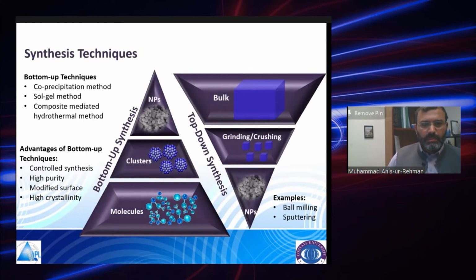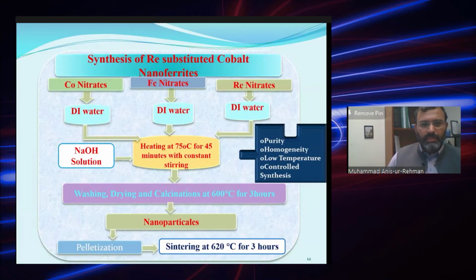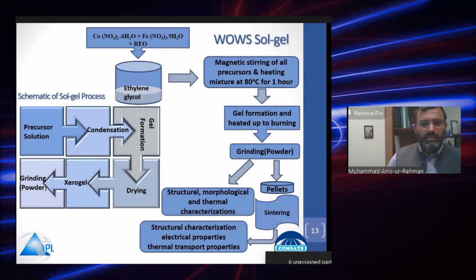Synthesis techniques are bottom up and top down. Bottom up methods are usually economic and can be easily handled. The materials we have prepared were made by two wet chemical methods. The first one is the co-precipitation method. The nitrates of the respective elements were dissolved in deionized water with a molarity of 0.4, and then heated at 75 degrees. After getting the precipitates, these are calcined and pellets are made for further characterization. The beauty of co-precipitation is that we can get purity and homogeneity, and it is a low temperature method. The other method we have utilized is the WOWS sol gel. It is a simplified form of the sol gel method in which, in a single step and in less time compared to other methods, we can get pure materials and a very small particle size.